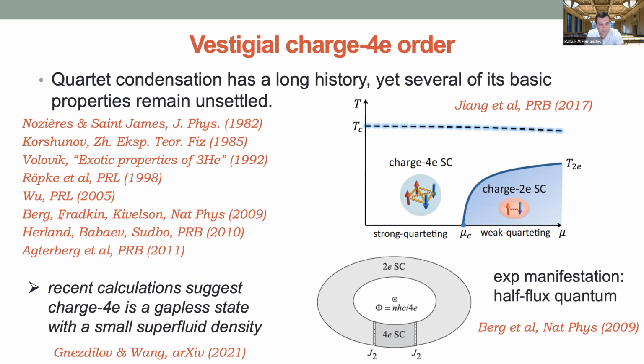There's this very nice paper by Erez Berg, Eduardo Fradkin, Steve Kivelson, where they show that if you had pair density waves, they could melt into a charge-4E phase. What we are saying here is that you really just need to have two condensates. Here, a nematic superconductor has a two-dimensional representation, so there are two different condensates, and they also allow for a charge-4E phase.